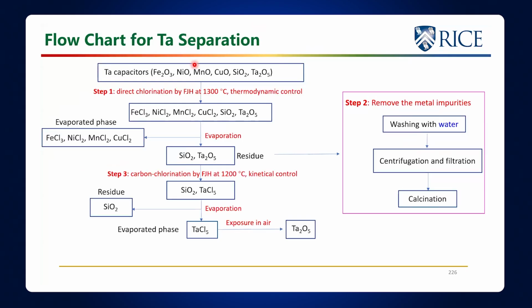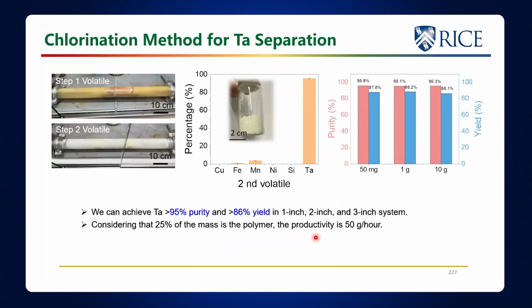So you take the tantalum capacitor and we do the direct chlorination. That gets rid of all of these metals, which come out in the evaporated phase, and then you just have silicon oxide and tantalum oxide, and then you do the carbochlorination. You get the tantalum chloride. Silicon oxide has not reacted. This goes in the residue. This evaporates out. When we expose it to air, it goes back to tantalum oxide. So you can see that in the first step, all those other metals came out. In the second step, just the tantalum chloride comes out, which then forms tantalum oxide. So tantalum was 95% purity, 86% yield, and so here's the productivity.